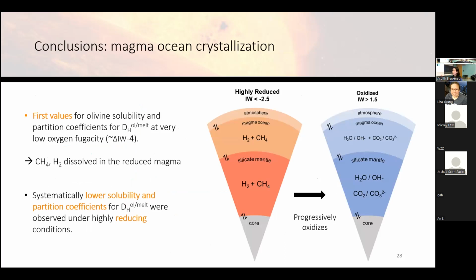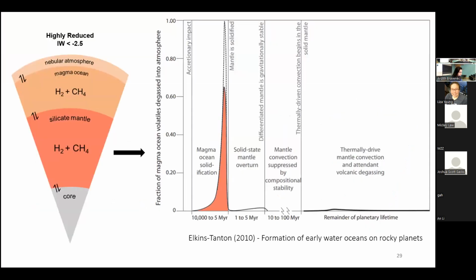But to summarize the important parts of this study, these were the first values for olivine solubility and partition coefficients in a very reduced system, where there's already been a lot of work done on glass. We haven't necessarily known how this affects crystallization. And we also see that we have systematically lower solubility and partition coefficients when it's reduced. Again, this is all important because we think that this might be a very prevalent stage in planetary formation and evolution, and it has very important implications for that early initial outgassed atmosphere.